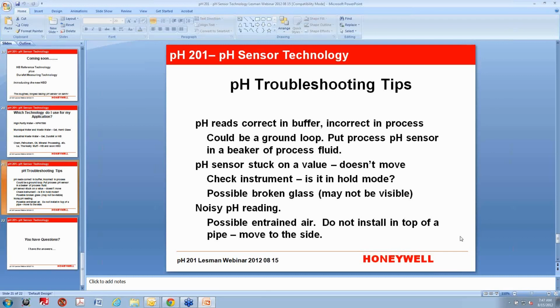A lot of times you can have a pH sensor in your process, and say your process is 9 pH, but it's reading 11 pH. And you're like, well, that's no good. But you take it out and put it in a buffer, and it seems to read correctly. The test would be to pull a sample of your process and put the sensor in a glass beaker or a plastic beaker, something that's insulated and isolated, and see if it reads the process correctly. If it does, that means there is a problem with the insulation. There is some voltage in there that doesn't belong, and it's upsetting the pH measurement.